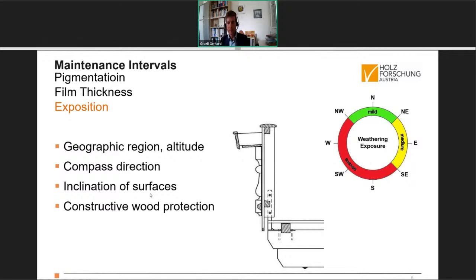And the inclination of surfaces is a very important factor for exposition. With a detail of a balcony, a cross-section of a balcony rail here, you can see that there are top surfaces of the handrail and of the flower tray here, where the top surfaces and also the floor of the balcony are inclined almost horizontally with only very narrow or small edges, small angles so that the rainwater can run off. Then there are vertical surfaces which are orange here, and there are green parts which are very nicely protected by other parts, sheltered by the decking of the balcony, and therefore very nicely protected from direct weathering.